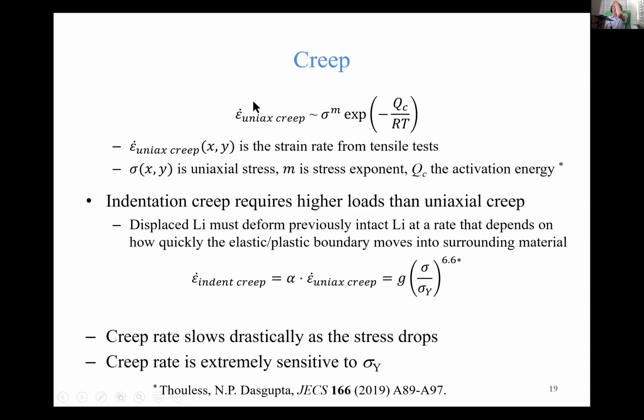However, you can't really use this sort of thing if you're thinking about indentation, because indentation creep requires higher load than uniaxial creep, for the same sort of reason. If you're indenting, the displaced lithium has to push against lithium that's already there. So the creep rate is going to be slower for the same force. And empirically, it turns out that there's a constant that involves the yield strength that can relate these two.